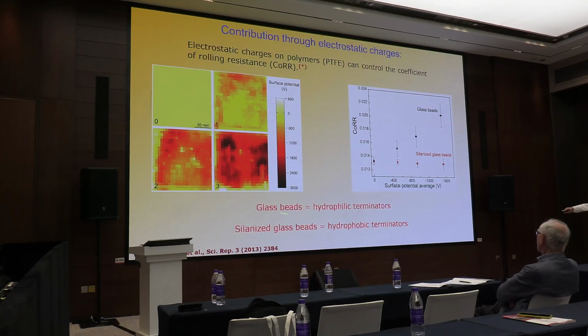And well, okay, the conclusion is that glass beads, little balls, are hydrophilic terminators. And with these hydrophilic ones, you have a dipole at the surface that interacts with different charges. But the silanized glass balls are hydrophobic terminators. You don't have a dipole, or the dipole is not strong enough.